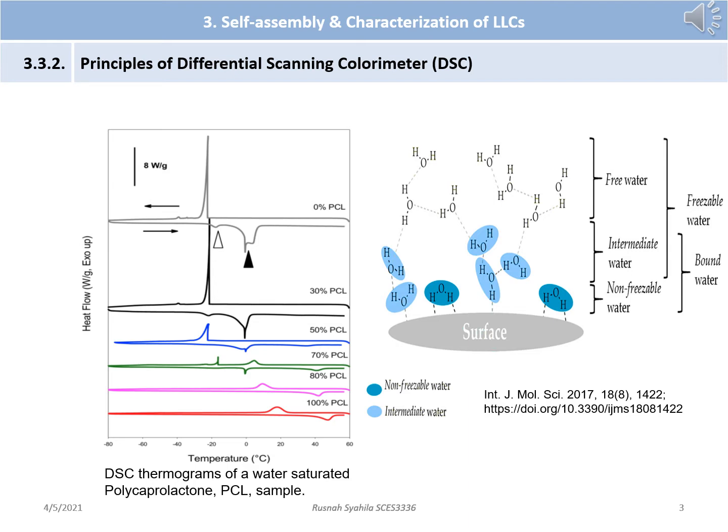Although two distinct water melting peaks around 0 degrees Celsius and minus 20 degrees Celsius are observed, only one sharp water crystallization peak appears in the cooling trace. According to the classification of three forms of water in the polymer, free water melts at 0 degrees Celsius, and a water melting peak at -20 degrees Celsius is attributed to freezable bound water.